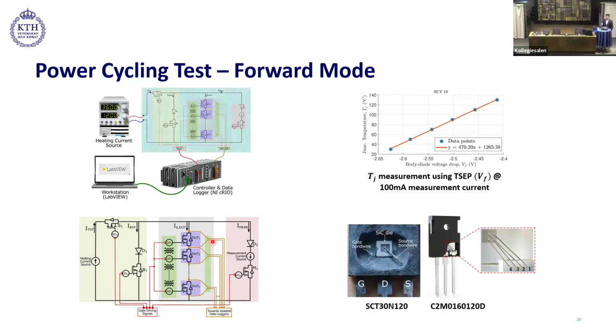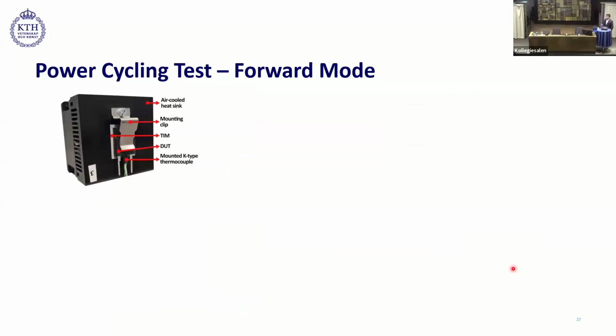We tested two different kinds of devices using this test. First one is from ST Microelectronics with single bond wire, and the second one from Cree, which has 4 bond wires connected in parallel. This is how the DUTs were mounted. So we had an air-cooled heatsink for each DUT, and then the DUTs were mounted on these heatsinks with the help of clip. We have a thermal interface material in between the heatsink and the DUT. During the test, we also measured the temperature of the middle leg with the help of K-type thermocouple.